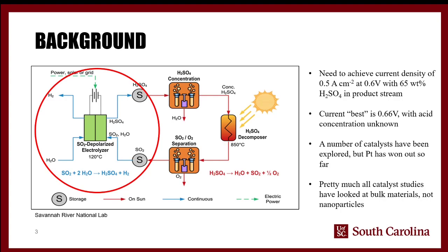Throughout the four or five decades of research, a number of catalysts have been explored: platinum, palladium, gold, iridium, ruthenium, their oxides, chromium, mixed metals, pretty much any noble metal catalyst that you can think of, and things like iron have all been looked at. Platinum has won out so far. There are some, like palladium, that were more active, but their stability was very, very poor. They wouldn't last more than a few minutes in the actual reaction. And so that's, of course, not any good at all. You need a catalyst that's both active and stable. And so that's why platinum has won out, as it tends to do with a lot of electrocatalysis.